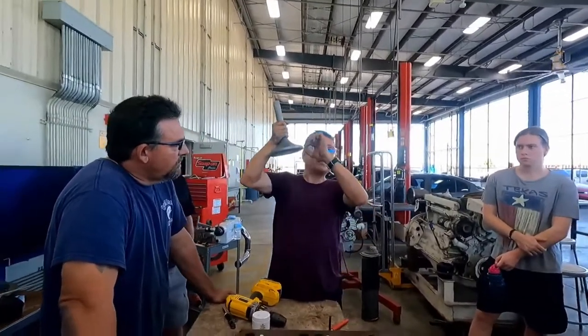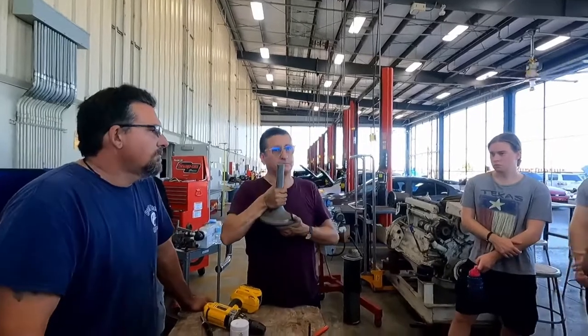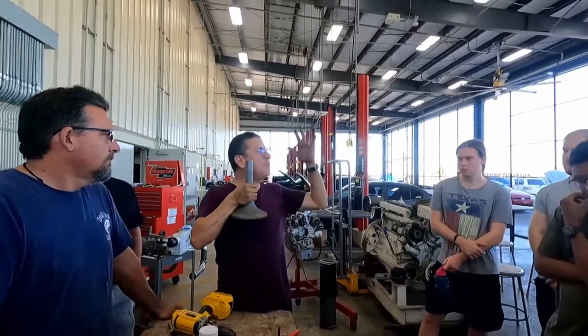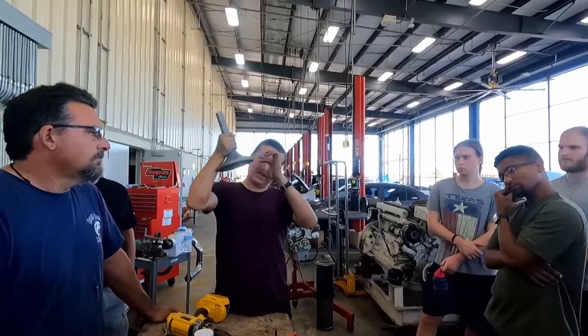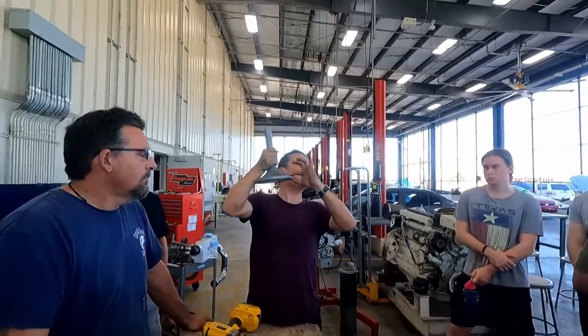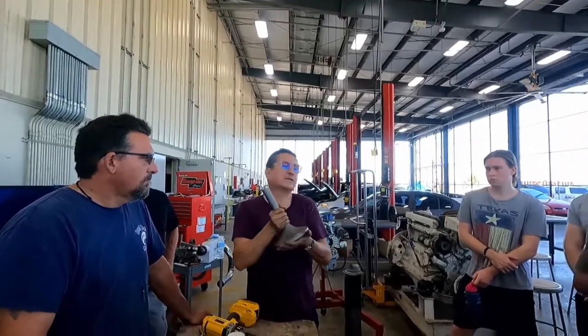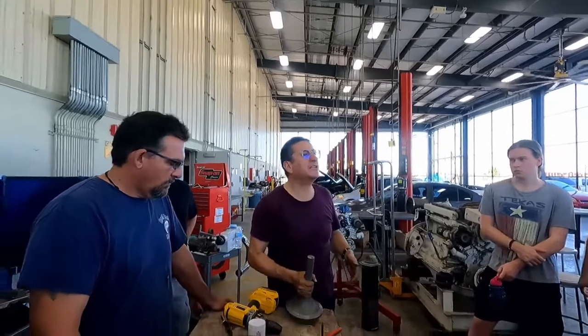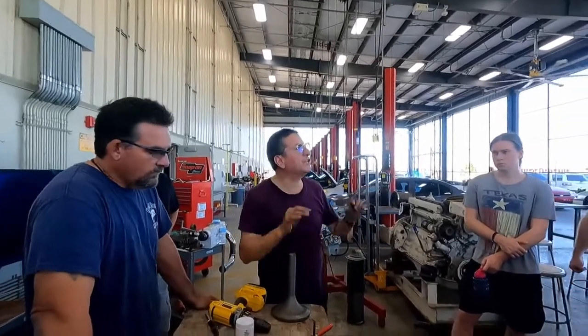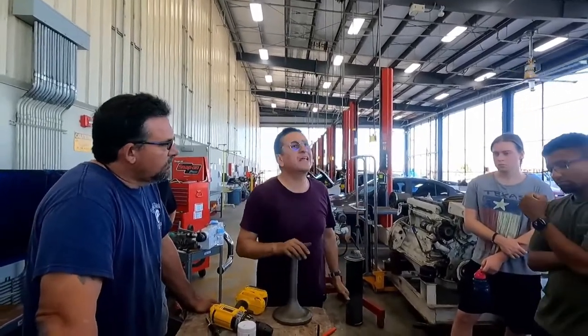The minimum distance recommended is 1 millimeter. This is the key word. 1 millimeter, this distance is the minimum. Of course, this is for a big engine, but in medium and small engines, 1 millimeter is the rule.